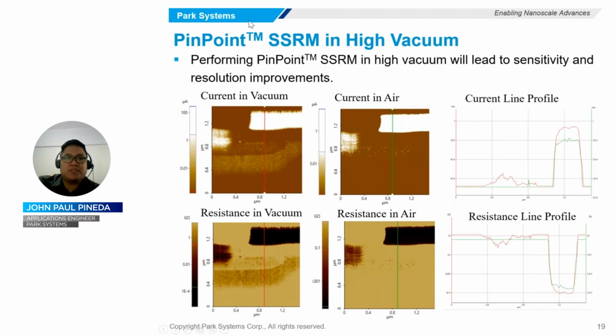To avoid contamination and obtain the best resistance data, it is recommended to conduct the test in a high vacuum environment. This will lead to sensitivity and resolution improvement. The images here show the comparison of current and resistance images taken in high vacuum and air conditions of a silicon carbide MOSFET. It can be observed that more features were detected in the resistance and current images taken in high vacuum compared to the ones taken in ambient air.